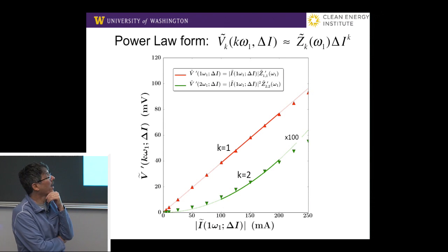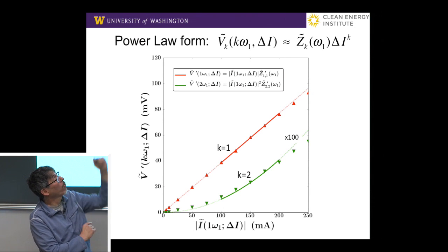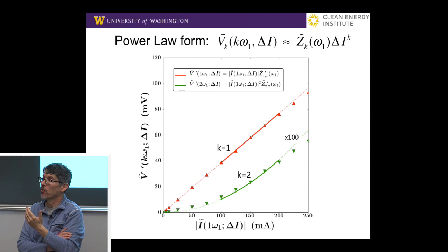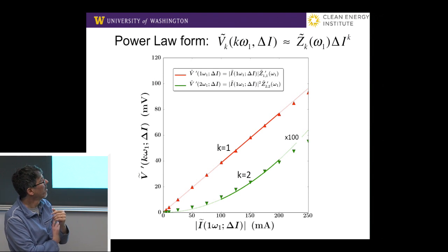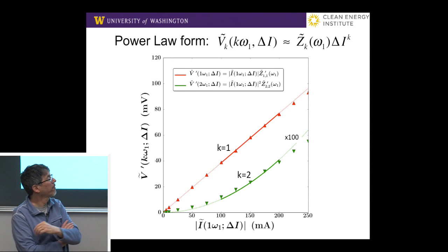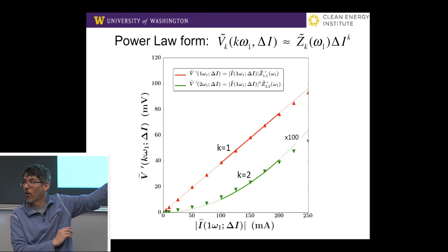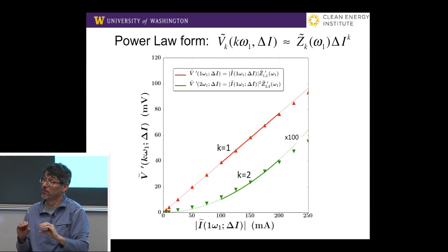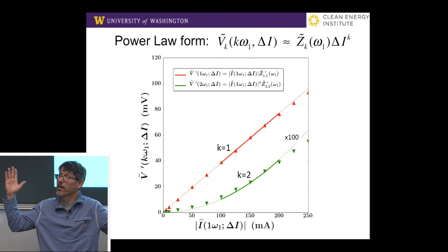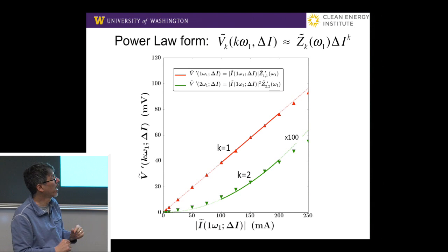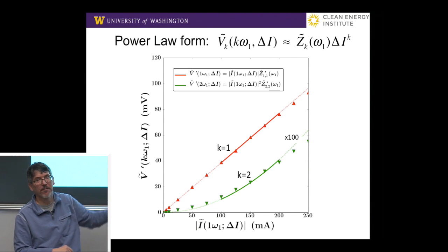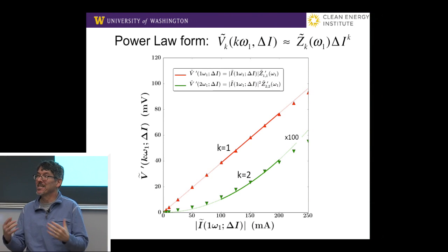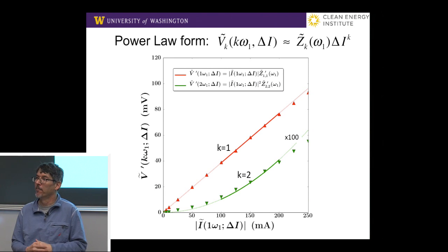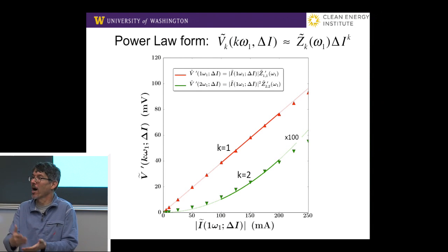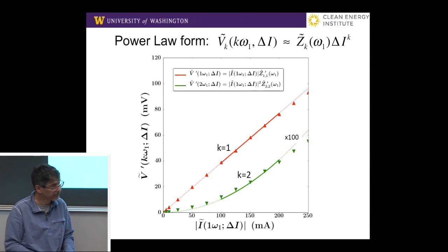So let's look at the second harmonic. The second harmonic, by this power law relationship, we'd expect would go with delta I squared. And that's more or less what we're seeing here. We see the curve is roughly parabolic. I've multiplied that curve by 100-fold because this is a tiny signal on top of a big linear response. There's a little tiny nonlinear response. And so the coefficient of that polynomial is going to be Z2, the coefficient associated with the second harmonic of the nonlinear response.